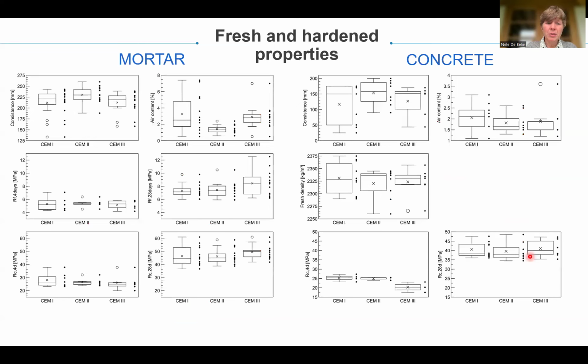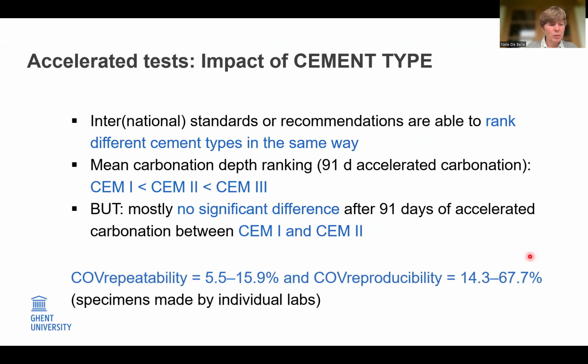The mix design and the curing conditions were such that the mortars or concrete samples were all of similar strength and consistency, independent of the cement type, actually. And the result showed, fortunately, that the different standards for accelerated carbonation were mostly able to rank the 3 cement types in the same order. So actually, the slowest carbonation for CEM1, followed by CEM2, and then CEM3 had the highest carbonation rate. Nevertheless, the coefficients of variance for repeatability and reproducibility in labs and between labs were quite high.